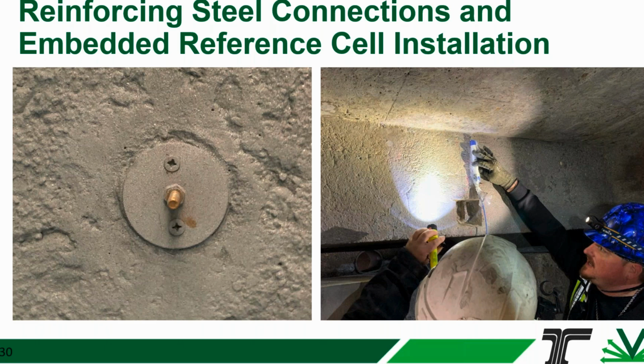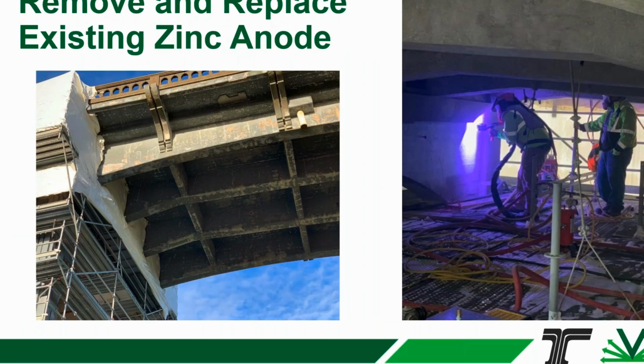So in terms of the zinc related aspect of the work, the picture on the left shows the condition of the zinc in 2020. So this is the 28-year-old system on the left. That zinc is removed, and then a new layer of zinc is applied to the concrete surface on the right. The removal was done by abrasive blasting, essentially as light as possible sandblasting to remove the existing zinc without damaging the concrete surface as much as possible.